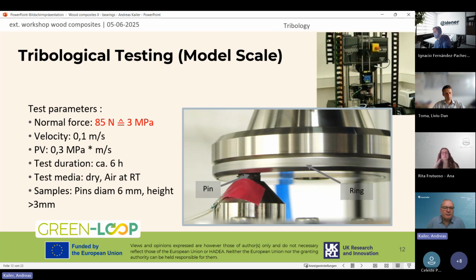With this type of method, we have used a normal force of 85 newtons, which corresponds to 3 megapascals, at a sliding velocity of 0.1, which makes this PV value of 0.3. The test duration was normally 6 hours, and we made mostly dry tests without lubricants, which gave the most interesting results.